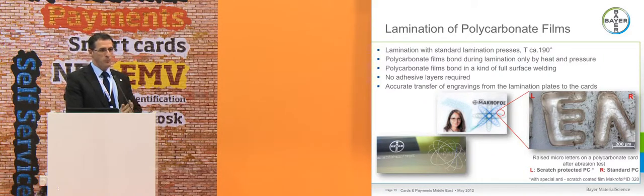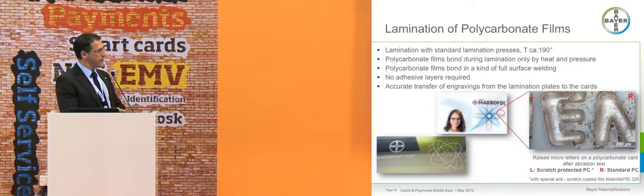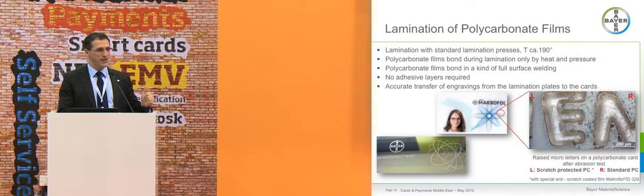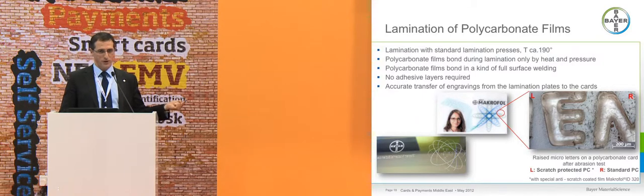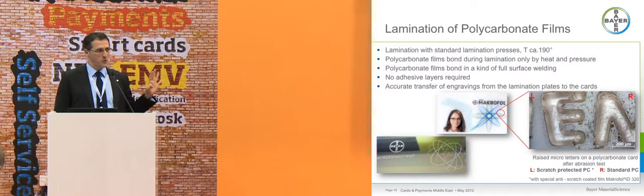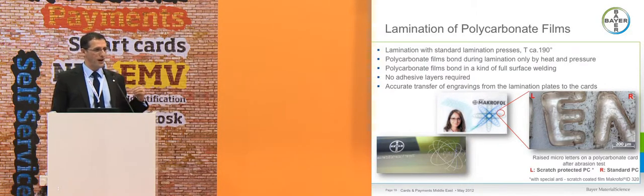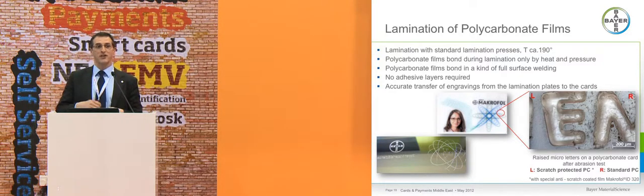Lamination. When it comes to lamination, polycarbonate has its strong point here because it doesn't need any adhesives in order to get laminated, and that is a very important point for the security of the document. In the ID documents world, adhesives are not so well seen because by exposing the document to maybe a higher heat, or by boiling the document, you can destroy the adhesive layer and open the document and change some things inside there, which is not wanted. Here, only by applying heat and pressure, you achieve a kind of full surface welding of the document so that you cannot open the document afterwards anymore.